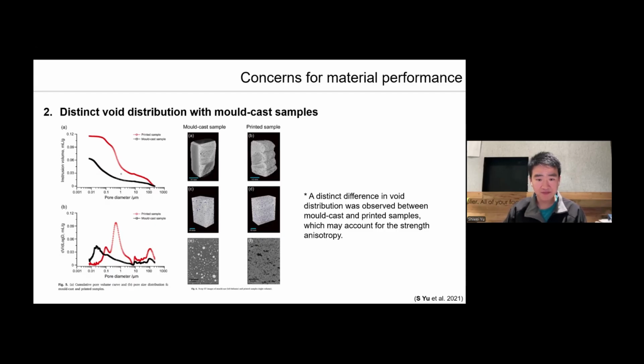To address this, we use defoamers in our mix to reduce the volume of the pores. The good news is that due to the high pumping pressure during the extrusion, it actually pushes many of the pores out, producing a denser microstructure. In fact, some researchers have even reported higher strength performance because of this effect.